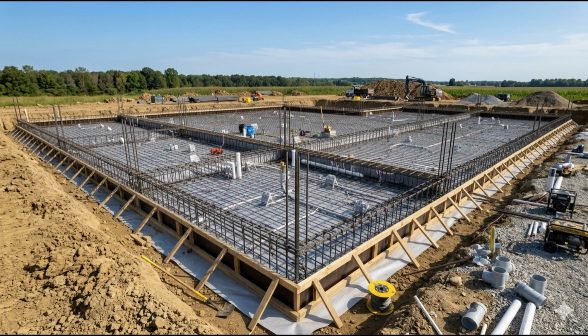Gerald checked the top mat similarly. One area near the northeast corner of the slab showed a bar spacing of 215 mm, slightly outside tolerance. He pointed this out to Jack, who promptly had it corrected. Gerald noted the correction in his inspection record. At 8 o'clock, he signed the pre-pour inspection certificate, confirming that the reinforcement was satisfactory to proceed with concreting. Roy countersigned it. Jack filed it.